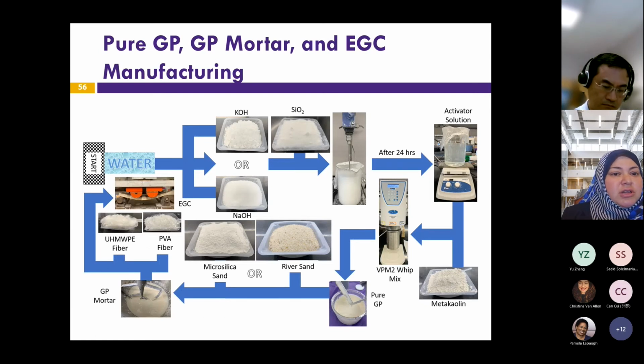This schematic shows the production method of the geopolymer or the EGC. We start first by dissolving the activator solution into DI water and mixing it for 24 hours. At first it's cloudy. By the end of the 24 hours, you see that it became clear. Once it becomes clear, then we mix it with the geopolymer precursor, metakaolin or the metakaolin fly ash combination, and that gives us the pure geopolymer.